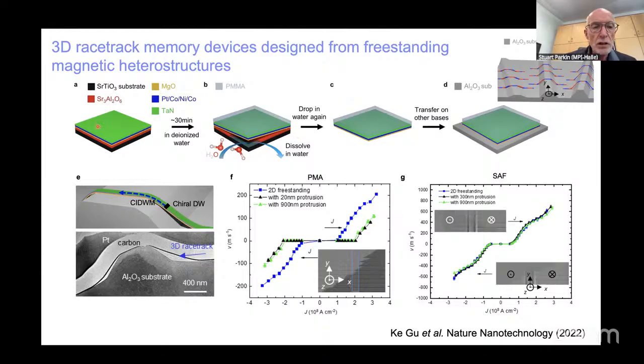This is on a 5 by 5 millimeter squared substrate. So what Kei Gu does, he dissolves this membrane in water after we've grown the racetrack. And then in water, he transfers this ultra-thin membrane, which now consists of just the tantalum nitride, platinum, cobalt, nickel, cobalt, MgO. He transfers this onto another substrate. In this case, as shown in the top right, he has formed in sapphire these little hillocks. These are up to 1 micron tall. And basically, he moves the racetrack on top of these hillocks.